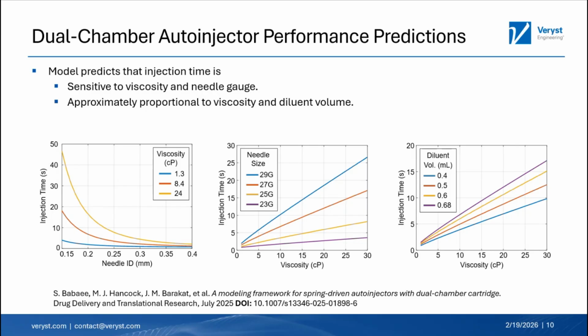Now, going one step further, for low viscosity drug product solutions, injection time is less sensitive to needle size compared to, say, higher viscosity solutions. Also, the hydrodynamic resistance is low for low viscosity drug product solutions. And so stopper friction, which is independent of that viscosity, plays a moderating influence. For high viscosity drug product solutions, the needle hydrodynamic resistance dominates stopper friction. And so injection times and flow rates inherit the hydrodynamic resistance's sensitivity to needle size.